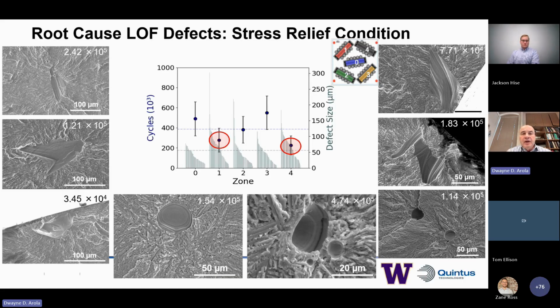I drive one more thing home, which is extremely important, and that is one of the major interests for us was the intra-build variability within our machine. So I'm showing you, if you could see on the upper right-hand corner region, a top view of our build layout with zones 1 and 4 near the back of the machine, 0 in the center, and 2 and 3 near the front. And what we're doing is plotting average fatigue life. This is for the vertical orientation for each of these zones for the 3 partners.